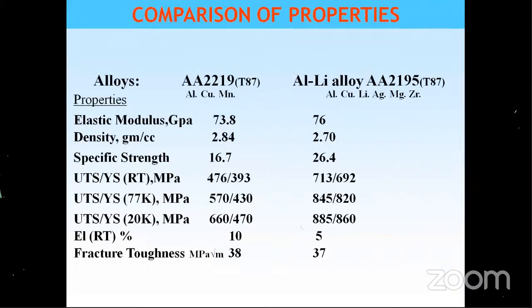Why am I after this one actually? I told you 1 kg of payload is nearly $20,000. If I use it for the C25, our cryogenic stage of GSLV Mark 3, if I change from 2219 to 2195, this is aluminum copper, that is aluminum lithium, I can increase the payload by very close to 250 kg. So imagine 250 into $20,000 is a huge amount. So that much payload gain, and it's not a joke. So we are working on that.